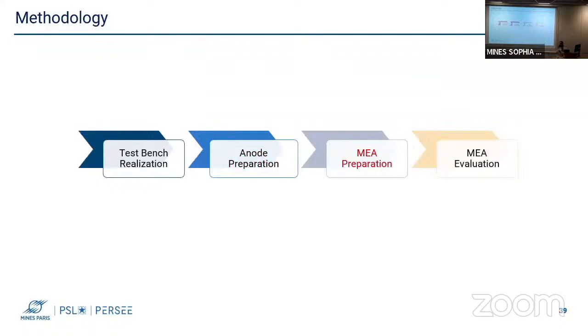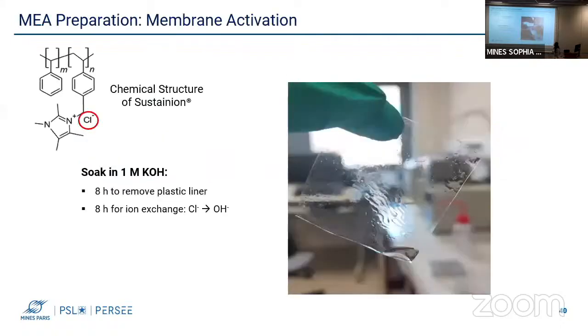After that, the MEA should be prepared, and we start with the activation of the membrane. The membrane chosen is a commercially available one, Sustainion, provided by Dioxide Materials. It has the following chemical formula, and it is received in the chloride form. These ions should be exchanged into hydroxide ones by immersing the membrane in 1 molar KOH for several hours.